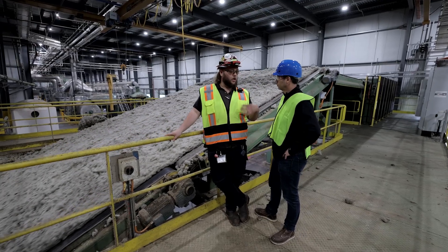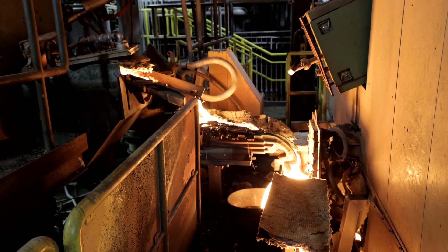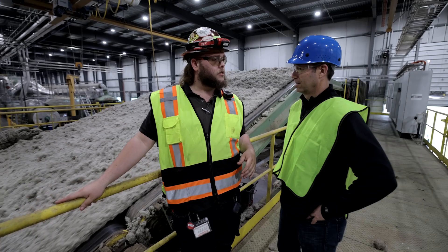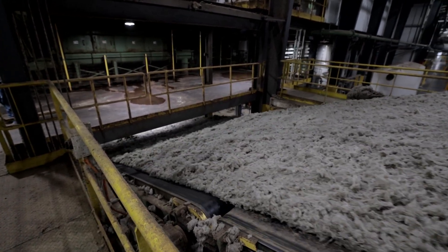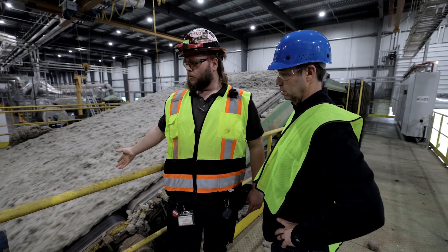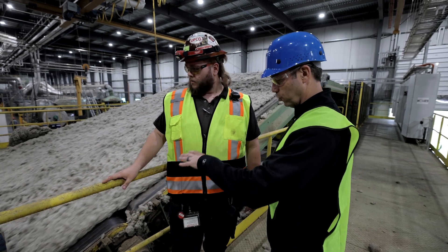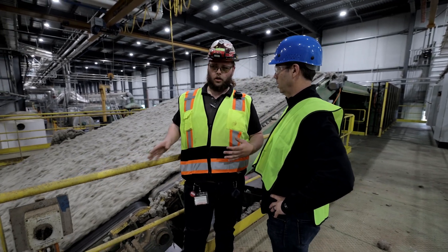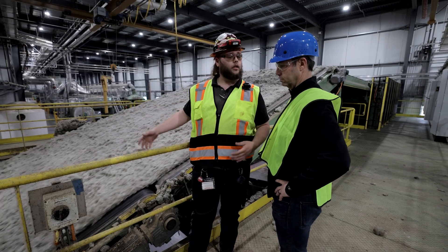At the top of the stairs, what we're seeing is the melting furnace. You see that stream of melt come out into our gutter troughs and be diverted to our spinners, which are essentially carnival cotton candy machines. The fibers are spun at high speed, and air pulls them off. It's being sprayed with resin and water, and then that web is conveyed by a large loop wheel, continuously moving with the line, pulling those webs off and releasing it into a single layer. That uniformity is really a true show of a good operator up in the melting furnace — they're controlling how that melt stream hits those spinners, and that's what produces such a beautiful quality web.